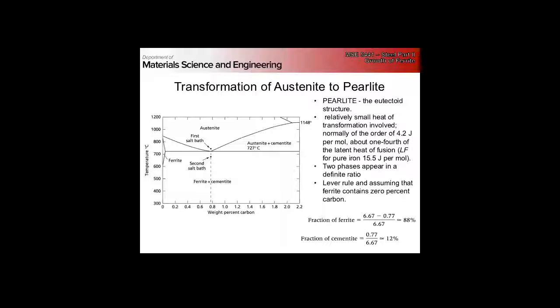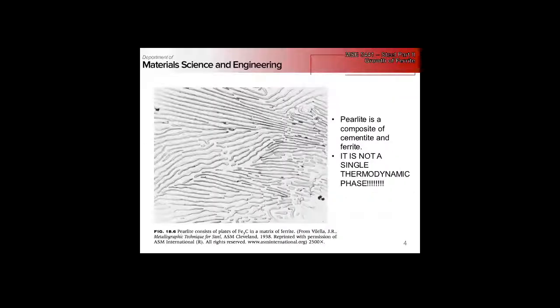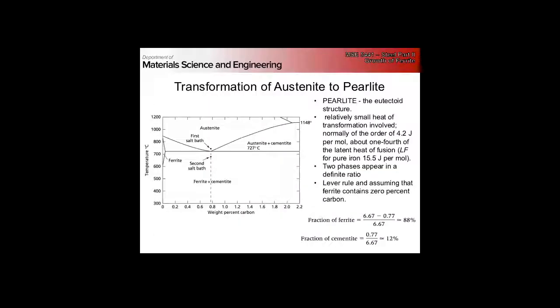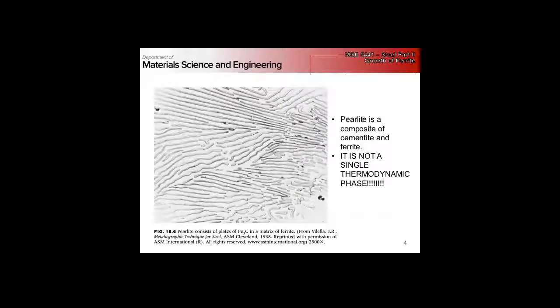So for eutectoid steels, we're actually 88% ferrite, 12% cementite, but looks can be deceiving, right? I'm sure most people would have said this is probably a higher cementite fraction than 12%, right? And it's also, remember, this is by weight here, right? So it's 12 weight percent cementite, not volume, right?